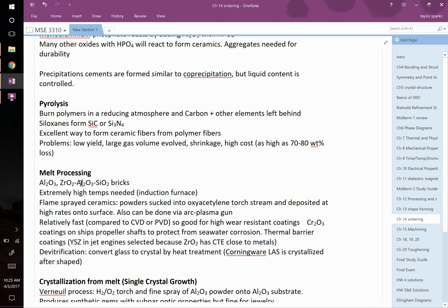Dr. Cutler's dad is famous for making silicon carbide. Dr. Cutler's dad founded our department, like in the 50s or whatever it was. He took rice hulls, the shell around rice, and he found out if you heat it, it's got pretty much the exact ratio you need of silicon to carbon to make very nice silicon carbide, right? So you heat it up in a pyrolysis type of situation, and you get a bunch of what they called whiskers. Nowadays we'd call these nanomaterials because it's nano everything, right? But really, really small particles of silicon carbide. And so there's a lot of people exploring how to make cool ceramics by doing pyrolysis.